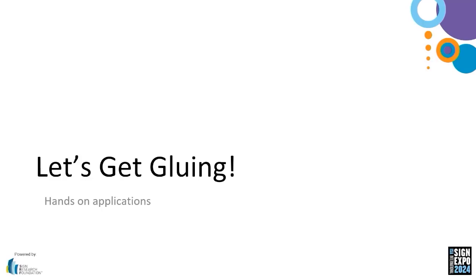I've talked about a couple of specific products. It's not supposed to be salesy, but you guys are asking for information, so I'm giving you answers. That's actually this product I used right here. This is the SignLock 810. A lot of people use the 406. The 810 is a low read-through adhesive, and it solves that problem by addressing those three factors. It has low shrinkage, it has a lower exotherm, it doesn't get quite as hot, and also it has high flexibility, 180% elongation, and a typical acrylic might be 10, 20, 30%. So it's much more flexible. So when that adhesive does shrink a little bit, because it's not zero shrinkage, the adhesive is able to give and expand and not force that line in the metal.